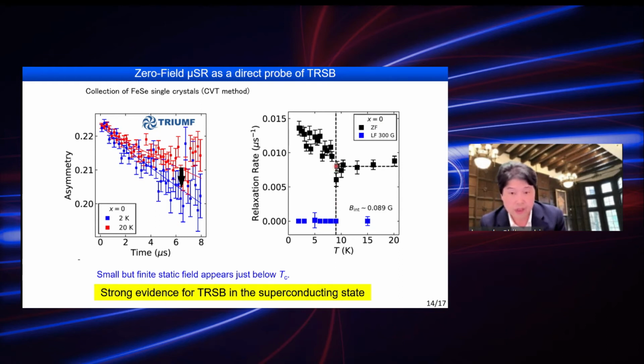This increase of the relaxation rate indicates that we have a small but finite static field appearing just below Tc, which gives strong evidence for time reversal symmetry breaking in the superconducting state of iron selenium.